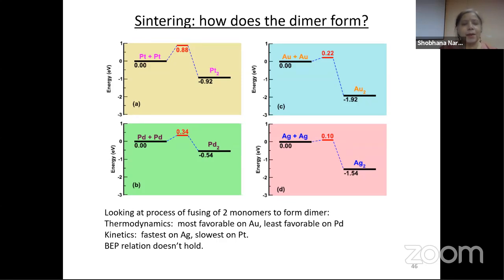For example, look at the upper left panel, when two platinum atoms come together to make a platinum dimer. And then I have compared it with gold, with palladium, with silver, etc. Incidentally, the interesting thing here is you find that thermodynamics and kinetics give you different answers. Because for thermodynamics, you look at how much the energy is lowered by. For kinetics, you look at the heights of the barriers. And incidentally, there's something known as the BEP relation, which says that these should both give you the same answers. And in these cases, that is not true. And that is because the transition states for these processes look very different from the final states. And that's because of these strange motions that you have.